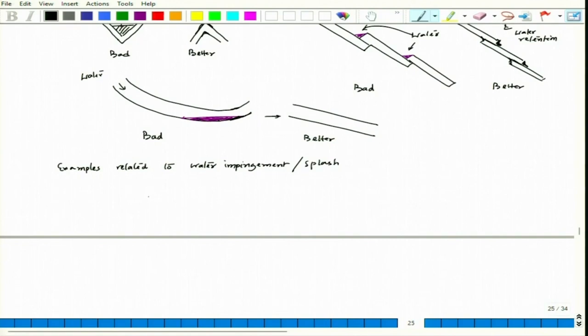Now, one possibility is, for example, you have a tank which stores dilute solution, and you are mixing concentrated fluid from outside, so there could be issues like this. For example, if you have a tank like this, you have an entry pipe, this is my tank, and let's say the water line is here. This is dilute, and let's say concentrated solution is coming through this pipeline. And this is the dilute solution. So this is coming and there could be impingement on top of it. And that could lead to splash. So this is the splash zone. Around this is a splash zone.